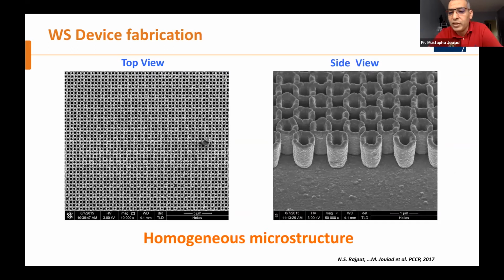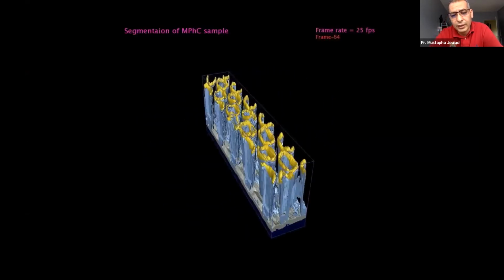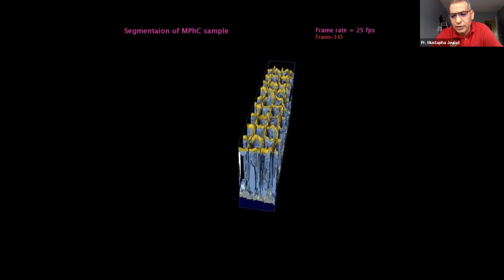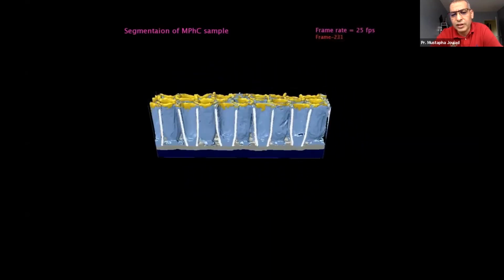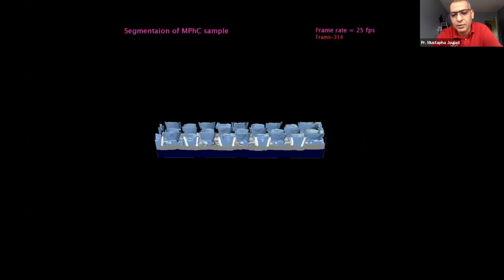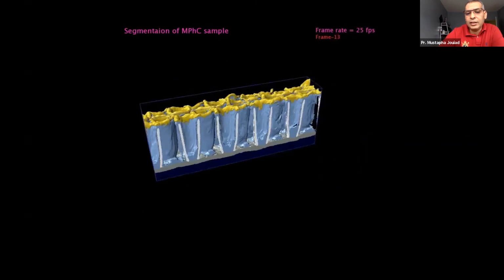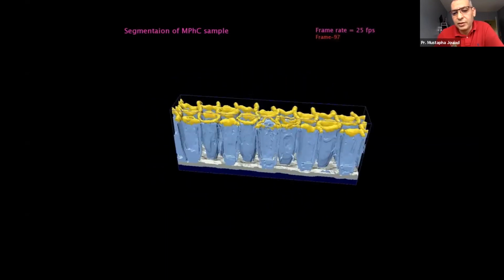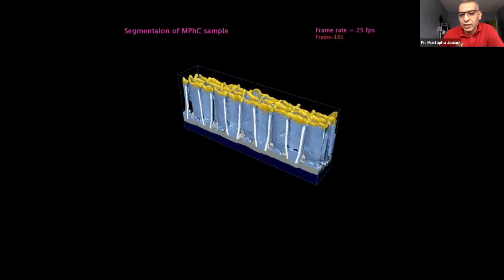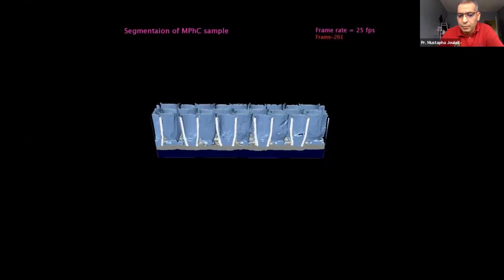So with the capillary, they can attract more water, and also it's double interest, these cups, because first they can trap water and they can trap also the light, because the light will be scattered inside that cannot be taken off from these shapes. So this is how the device looks like in 3D, and you can see most of the gold is on the top and the middle of the cups, and you have the stand, and this is reconstructed 3D using slice and view technique by FIB-SEM.